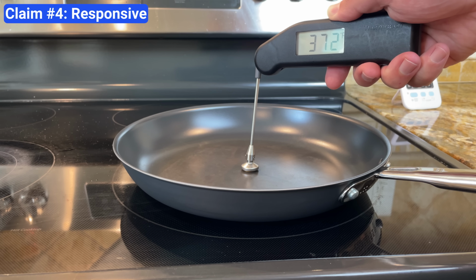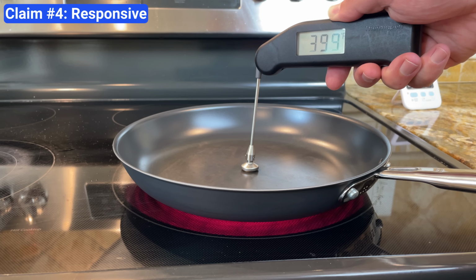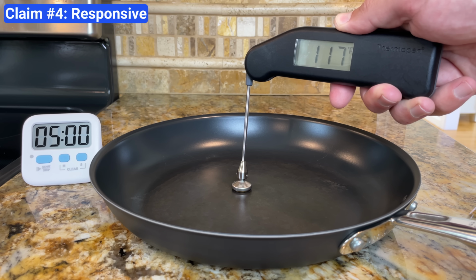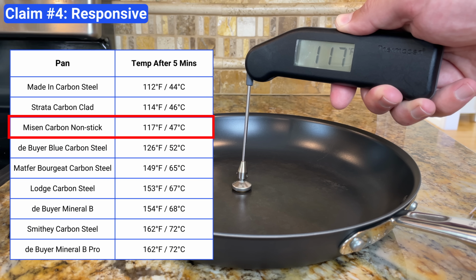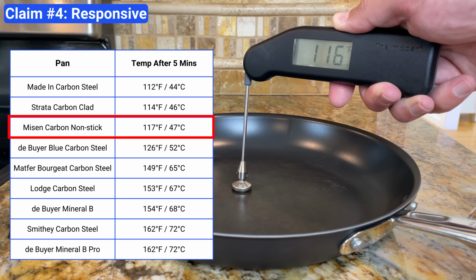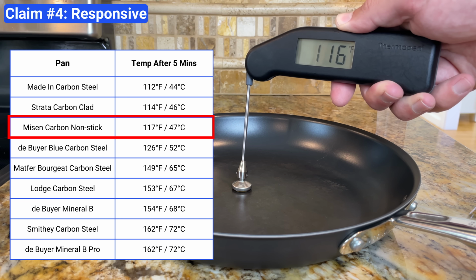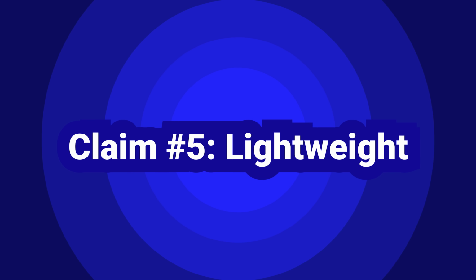To test heat retention, or how fast it cools, I heated the pan to exactly 400 degrees Fahrenheit, removed it from the heat, and measured the surface temperature after 5 minutes. It was the 3rd fastest carbon steel pan to cool down. So in terms of responsiveness and even heating, Misen lives up to its promises.